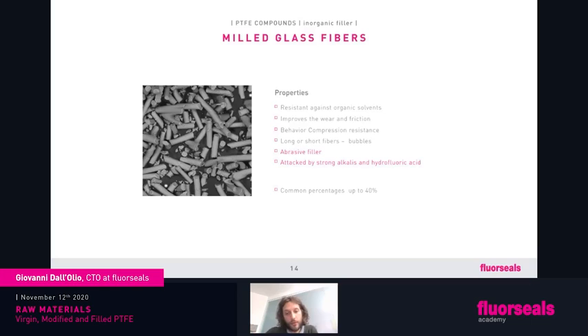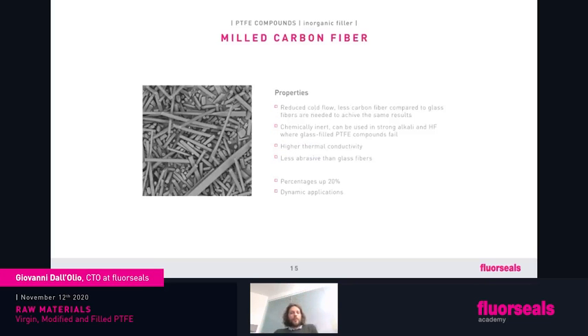Also, the chemical resistance is reduced because the glass does not have the same chemical resistance as PTFE, so it can be attacked by strong alkalis and hydrofluoric acid. This means that glass-filled PTFE is not always the best choice in chemical environments, but only in a few applications. Commonly, we can produce PTFE plus glass up to 40% of glass. So we have mentioned that glass is a very good compound, widely used, but has some weak points.